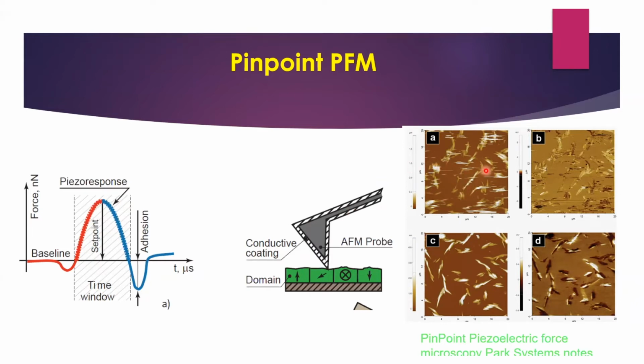Here on the right, there is an example of a sample that is very, very soft. And if you try to measure PFM with the typical scan of the tip in contact with the sample, you cannot obtain a good measure, because you're going to separate the material with the tip, and you're going to have problems obtaining a good piezo response signal.